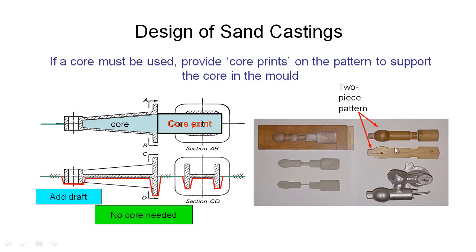If the core is the same size, then it's going to fill it completely, and so that's why it's a core print. So in this final part, you can see this is the bit that we're interested in here, and it's going to be hollow because the internal cavity is filled up predominantly by the sand, and then we have the shell of metal around the outside. And this bit here is the gate and the sprue, and probably part of the runner as well. This is basically where all the metal has come into the part, and we would cut this off and throw this back in the pot and melt it down and use it again in the next casting.